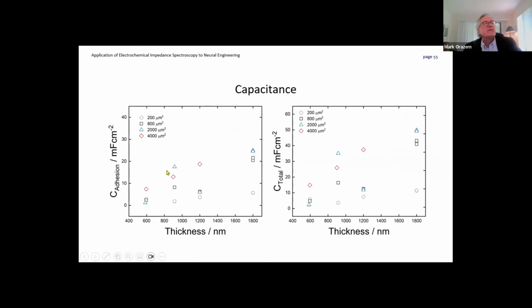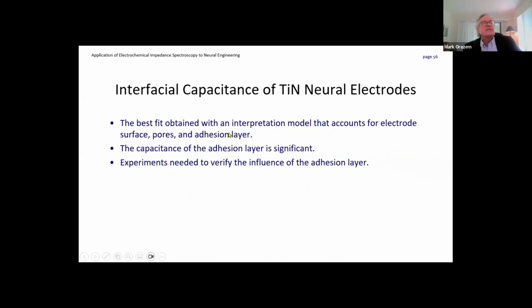The capacitance we're getting for the adhesion layer is somewhere on the order of, let's say, 10 to 20 millifarads. And the total capacitance of the system can get up to about 50 millifarads, depending upon the thickness of these layers and also the area of the electrodes. So the point is that the best fit we got accounts for the electrode surface, the pores, and the adhesion layer. And the capacitance of the adhesion layer is significant.